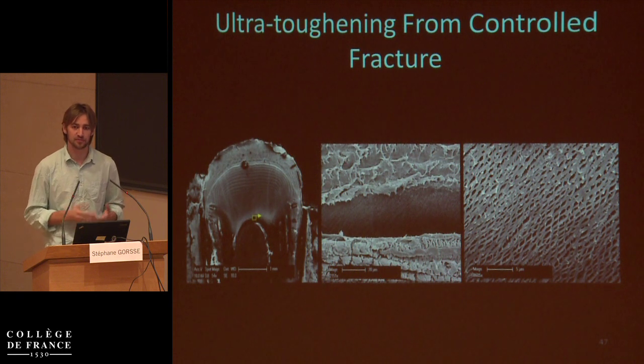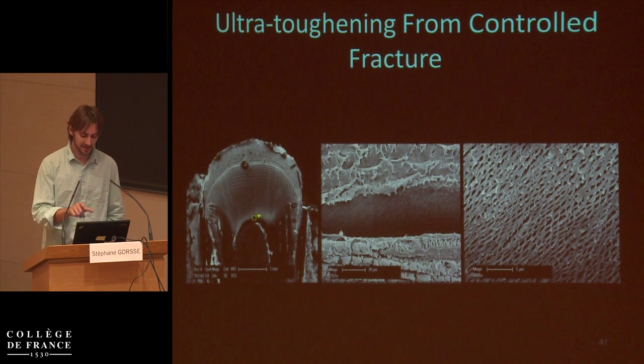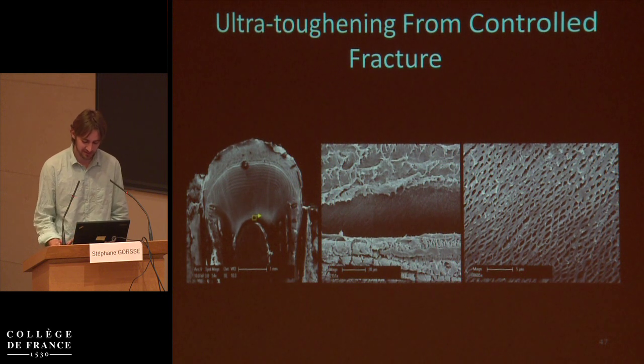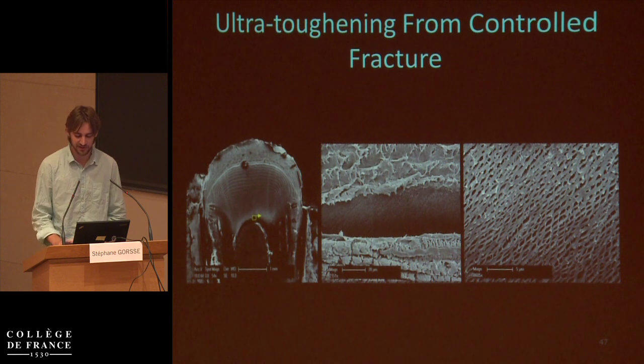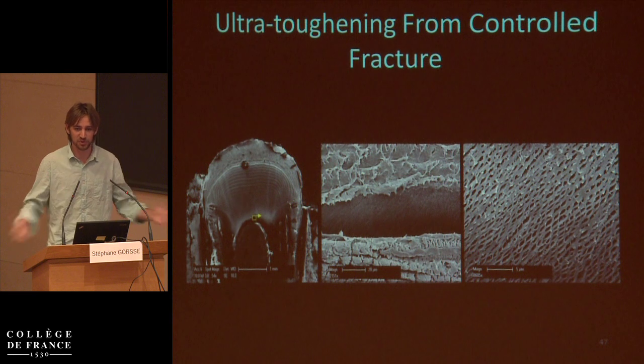And so you really just have a marginal increase in toughness, because all you've done is mildly increase the tortuosity of the fracture. You just increase the fracture surface area. But this is what's clever about life, is it does things that we would never think to do, and that we try and remove all sources of failure. And what this organism has done has said, if you can't beat it, join it. Put the failure everywhere.